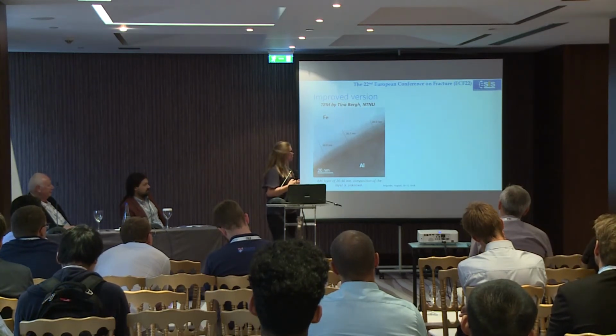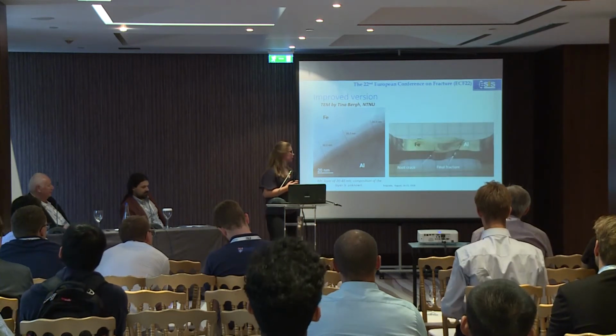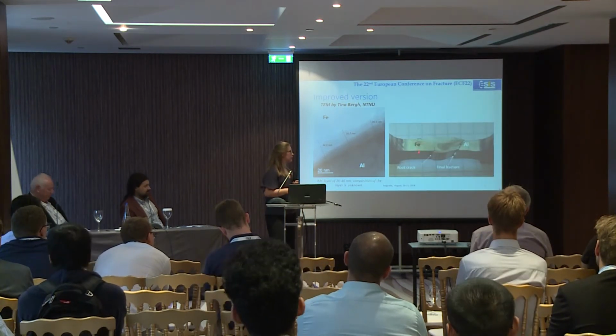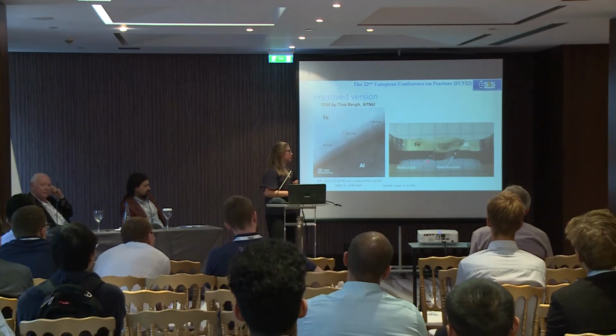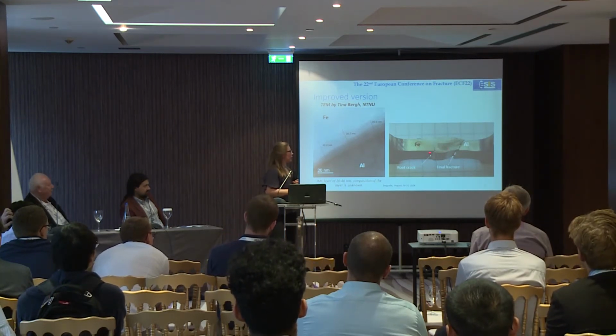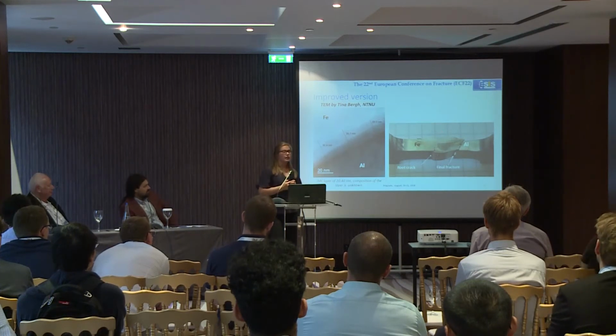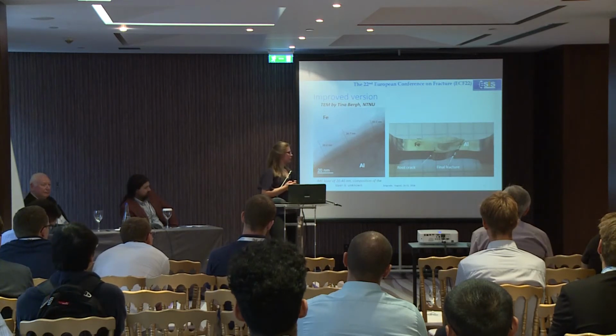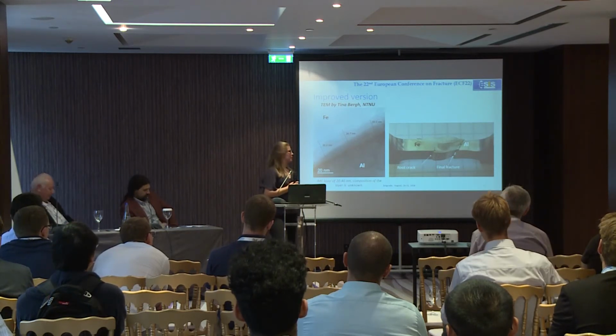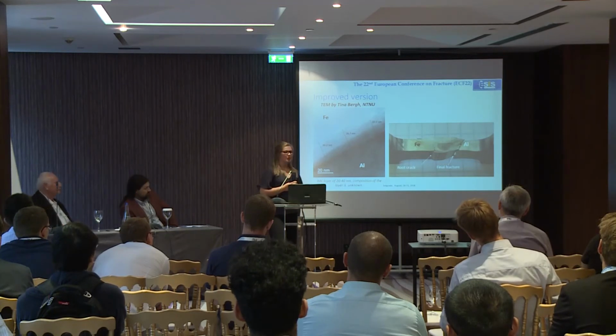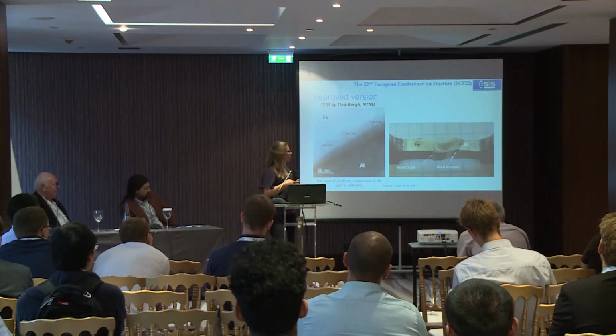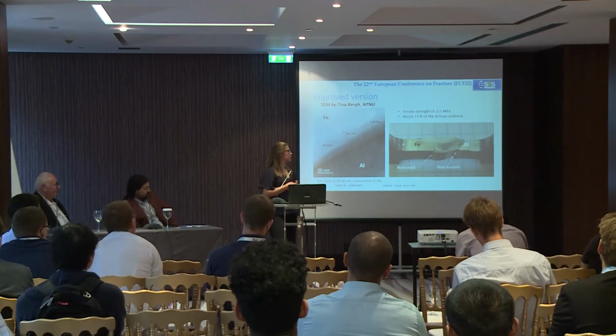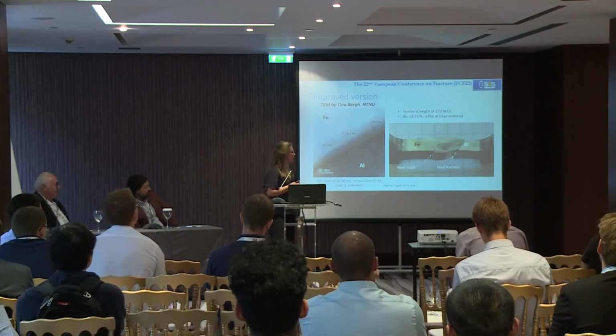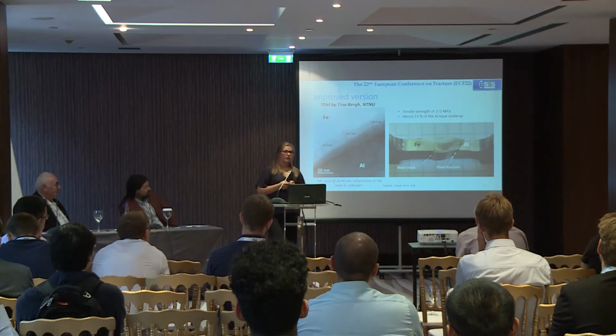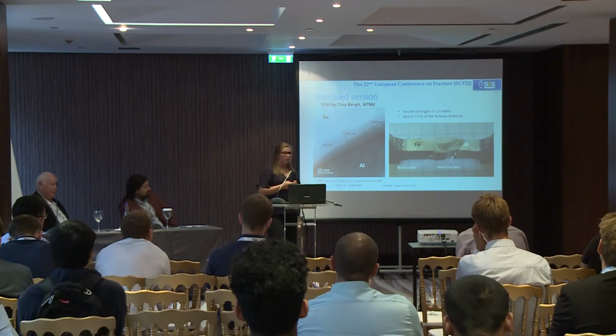Also, there was some tensile testing done on this joint, and here you can see that even though you have a root crack between the aluminum and steel, the final fracture occurs in the heat-affected zone on the aluminum side, which is really interesting, I think, because the heat-affected zone in the aluminum should be the weakest part in this case. Also, we found a tensile strength of 273 megapascals, and this is about 73% of the aluminum base material.